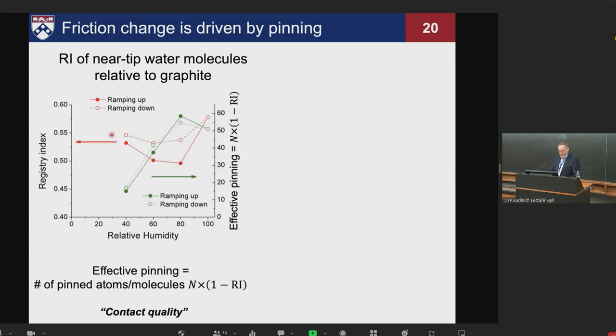So first, this is a plot versus relative humidity of the registry index in red. And we do it, this is again in the simulation, as the humidity goes up, and as the humidity goes down, so ramping down, just to check for hysteresis. There's a little bit, but the key point is we see that the registry index is high at first, so lots of unfavorable sites, then more favorable pinning, and then finally at the highest humidity, the registry index goes back up. Okay, the water is no longer in very many favorable sites.